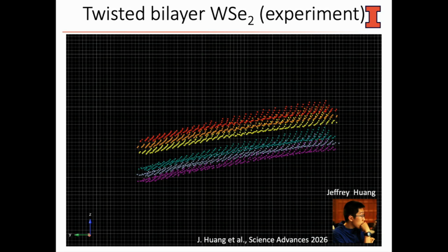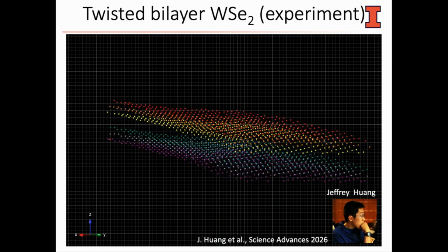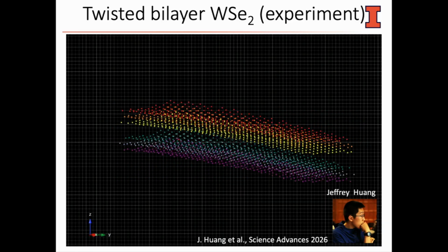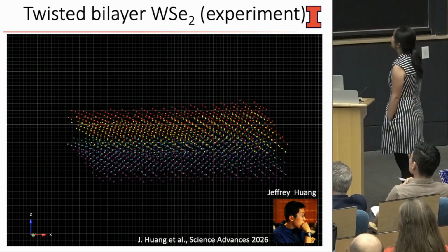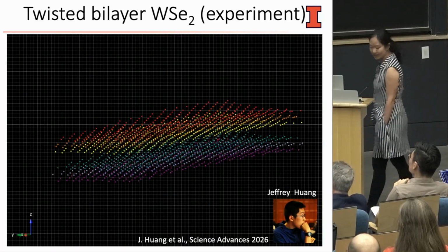And for very thin samples like this, it turns out that taking that information and then augmenting it with a couple of priors, namely that atoms are discrete objects that are spaced an average of whatever the spacing of this material is away from one another, you can recover in 3 dimensions the entire atomic structure of this system with something like 5 picometer precision in all 3 dimensions.